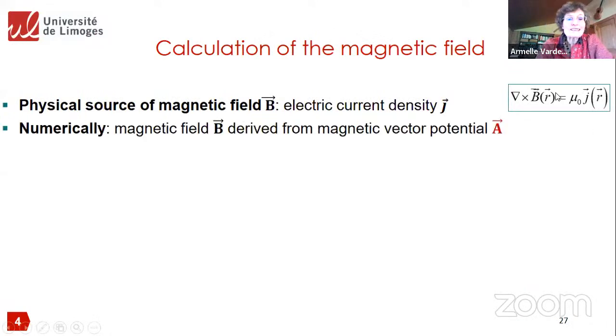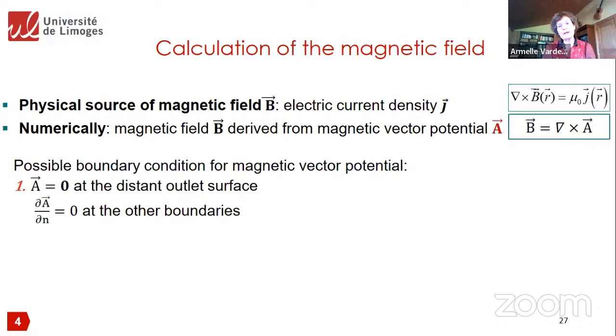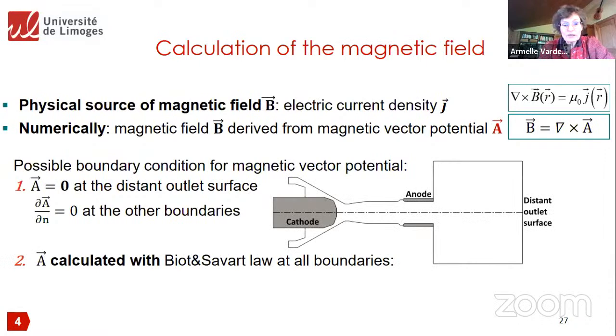Okay, but in the numerical work, it's different. The magnetic field will be derived from the magnetic vector potential A by this equation. Okay, so when you think about the boundary conditions, you have not to think for B, but for A. And generally, there are two types of boundary condition we can use. One is to impose some null flux at all the boundaries except far from the arc, where you put the value equal to 0. The other boundary condition, which is perhaps more demanding, is to calculate the value of A at all the boundaries by using the Biot-Savart law.